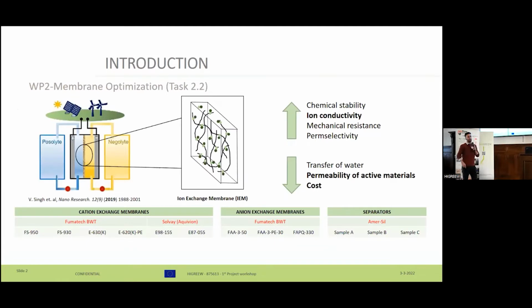So, first of all, an ion exchange membrane needs to fulfill the following characteristics. It needs to be stable in the media of operation, as well as having the best ion conductivity possible to avoid high overpotentials of the cell. It must resist during long periods of time, so mechanical strength is required, as well as good permselectivity to get high Coulombic efficiencies. And on the other hand, regular transfer of water. This is related to the difference of osmotic pressure between the tanks. So we need a balanced system to avoid undesired thermodynamical processes, such as the permeability of the active materials, which needs to be the lowest possible, and be competitive in terms of cost within the market.